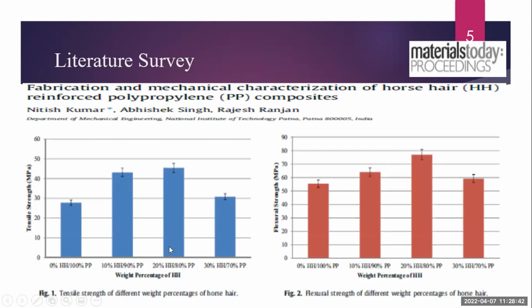It means if we mix 20% hair fiber into 80% polymer, it can give us good tensile strength. Similar results you can see in the flexural strength. Again, they tested the same samples to find out the flexural strength. Again, you can see that the composite having 20% horsehair and 80% polypropylene shows good results.